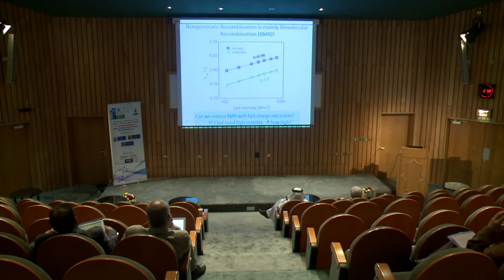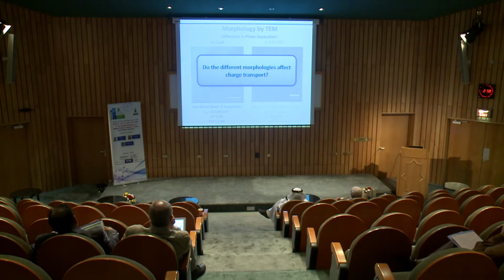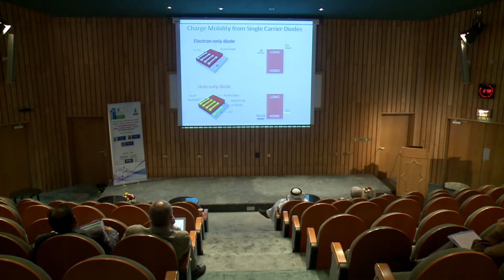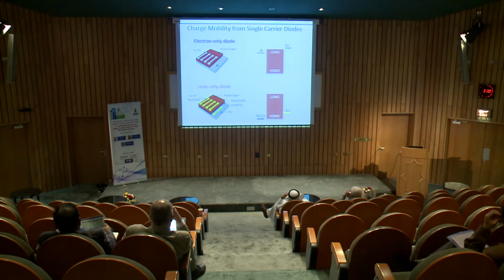To really understand charge extraction and mobility in our system, we now go on and measure the mobility. The way we measure the charge carrier mobility in our solar cell is by fabricating an electron-only diode, where we sandwich our blend material between a pair of low work function electrodes. When you do that, you ensure that electrons are the only carriers injected into your device, and they will transport through the PCBM domain, and you measure electron transport. For hole transport, we fabricate a hole-only diode, where we sandwich our blend between a pair of high work function metal electrodes. A lot of the time we basically use PEDOT:PSS, capped with aluminum or gold. When you do that, you ensure that the major transport carrier in your device is holes.